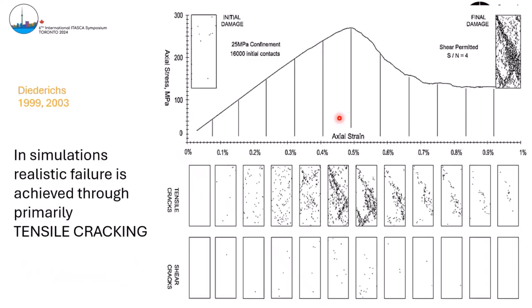So I took that in the early days, and this is fairly simple. You'll see a lot of versions of this, but it was kind of eye-opening at the time that you could create totally realistic fractures, or totally realistic yielded samples, which appear to be shearing at the end of the day, almost entirely from tension cracks. These are axial, more or less pseudo-axial tension cracks within PFC, particles pulling apart, very few shear cracks except right at peak. But this idea that most fractures could be entirely induced by the onset of these microfractures.